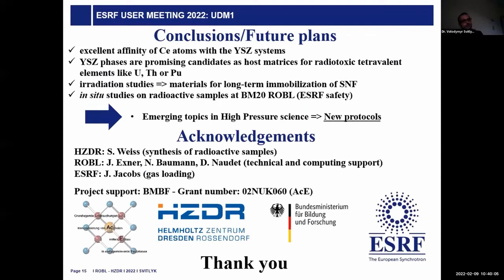So, conclusion for the scientific part: these experiments showed an excellent affinity of these cerium atoms with these yttrium stabilized zirconia systems. So these yttrium stabilized zirconia phases are promising candidates as host matrices for radiotoxic tetravalent elements like uranium, thorium, or plutonium for long-term and secure storage of radioactive waste. Next, we are planning on these systems to perform radiation studies, to simulate the influence of radiation during long term, and then we can conclude on their performance.